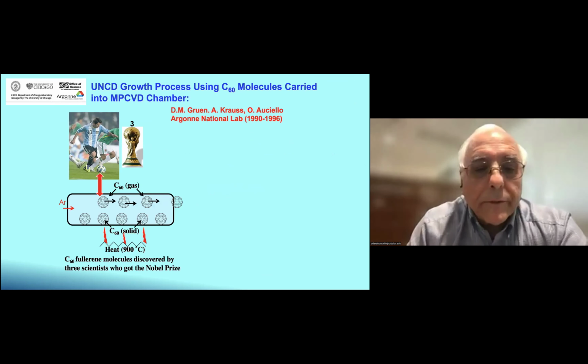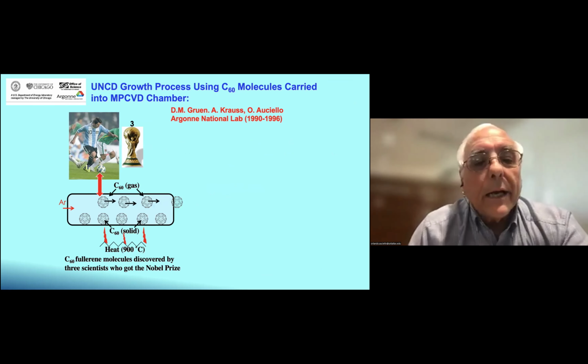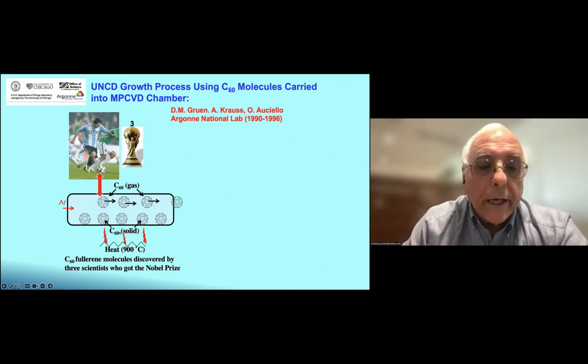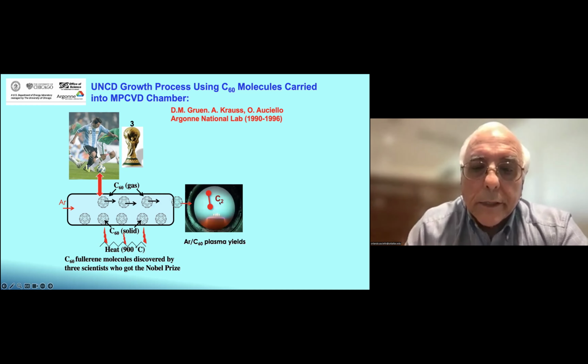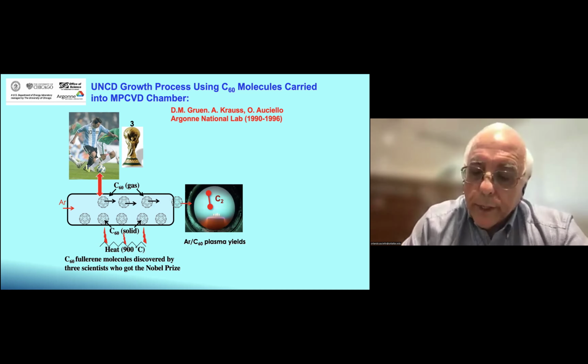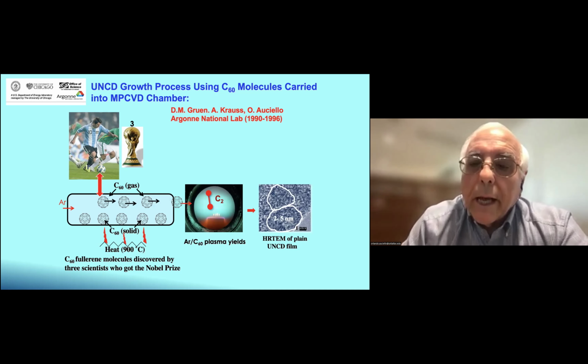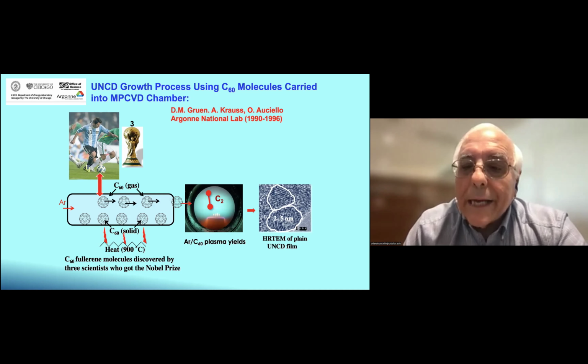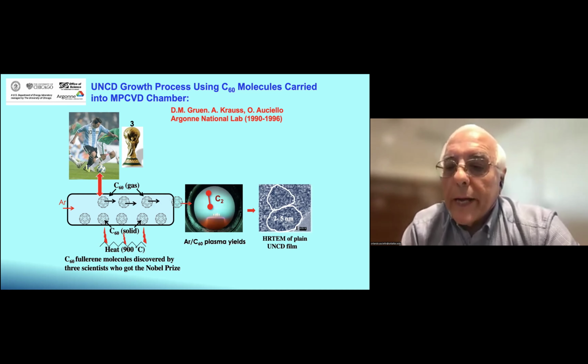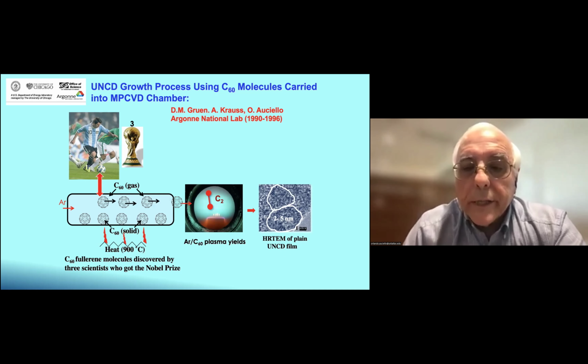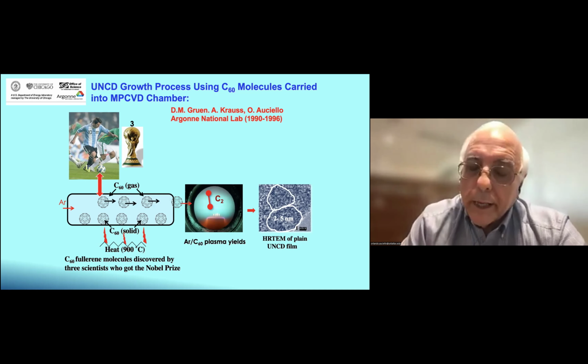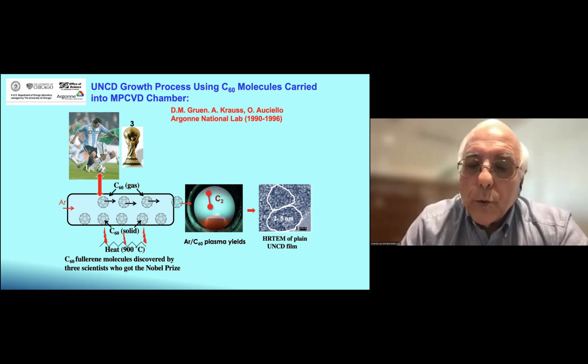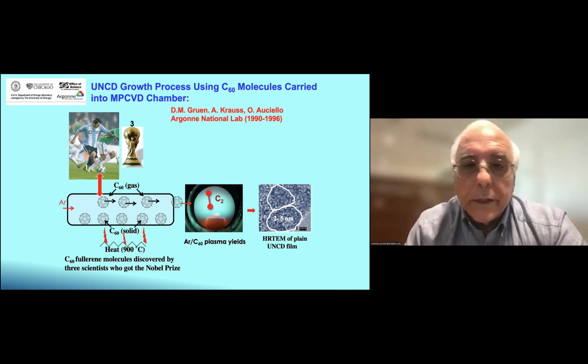We bought 10 grams of C60 fullerene in 1990, and that was $5,000. We put it in an oven, heated to 900 degrees, brought the C60 into the gas phase, flowed argon into the vacuum system, and we saw this green plasma. We didn't know initially what the green was coming from. But when we did the TEM analysis of the film, we saw that the grain size of our polycrystalline diamond films was 2 to 5 nanometers, which still is the smallest grain size of any polycrystalline diamond film in the world. And that's why we coined the name UNCD, ultra nanocrystalline diamond, or UNCD for short.